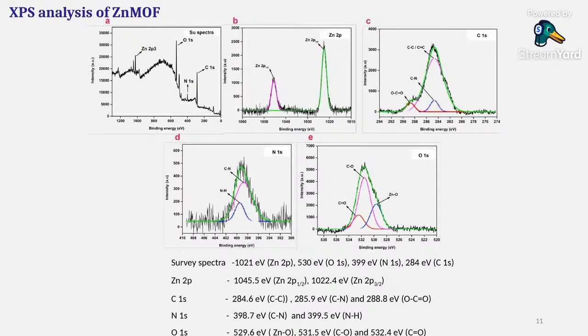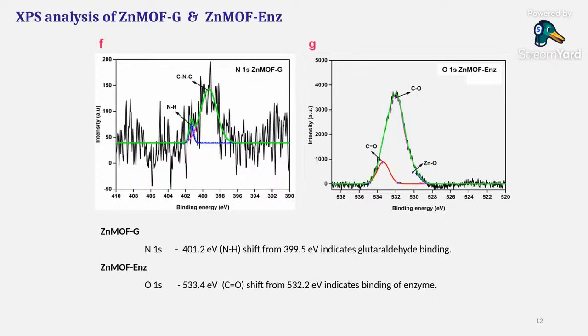Once we did it, we did the XPS studies, where you will see what kind of linkages are happening. We did it for the zinc MOF and the enzyme coated on the zinc MOF surface. Here you can see different electron beam patterns for the zinc, for the zinc MOF glutaraldehyde and the zinc MOF enzyme. You can see how the energy levels shifted from the unmodified to the modified surface.